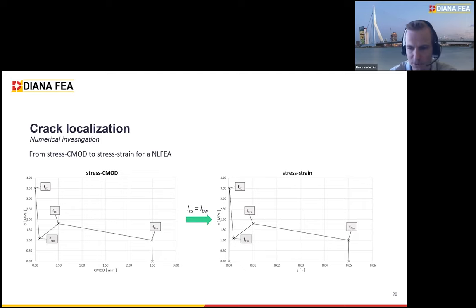However, for finite element models, the characteristic length is actually equal to the crack bandwidth. The reason for this is that we are not going to smear out the entire strain over a crack spacing, but we would like to only see it in one element. So we would like to localize the strain in one element. Then we can just make use of the crack bandwidth. And if we do it in that way, we can actually calculate the correct crack width in the end. I will further elaborate on this in the next few slides.